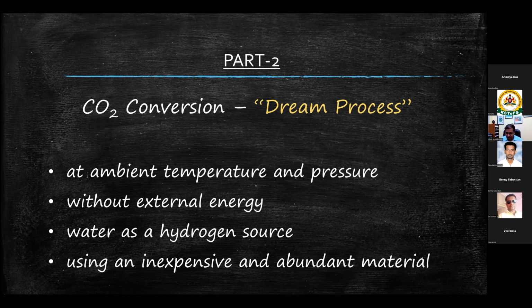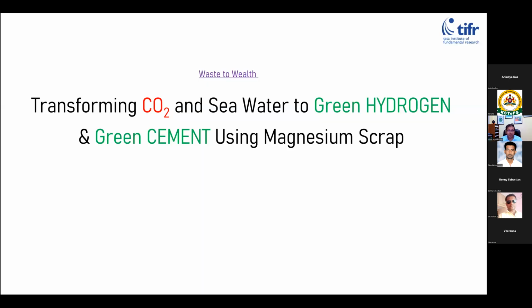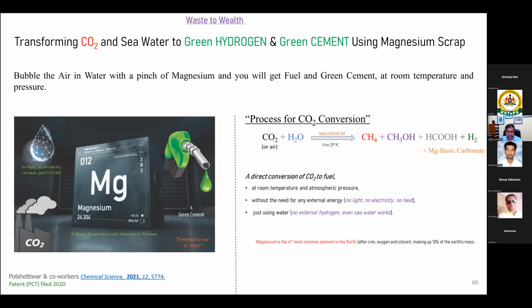Theoretically, it seems impossible. We luckily came across this process. What we observe is, if you take magnesium nanoparticles in water and just bubble the CO2 through it, all the CO2 reacts with water and magnesium and converts that CO2 to methane, methanol, formic acid, hydrogen, and magnesium basic carbonate.